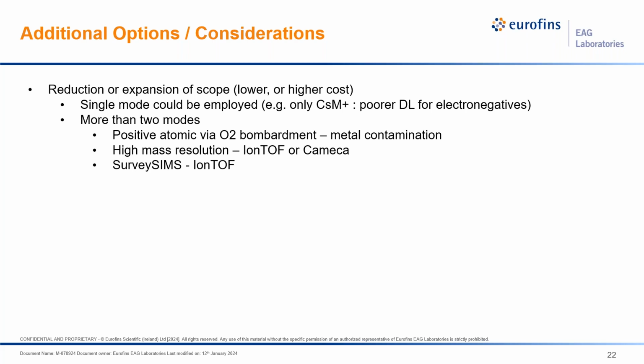So we could also do positive atomic data using oxygen bombardment, looking for other metal contamination. We could also use a different tool, so a high mass resolution is possible on either a time-of-flight tool or a CAMECA tool. This is particularly important if we suspect that some contamination might be a mass interference with something else, and we need to get the true profile. And furthermore, if we need to take a total mass survey without knowing the elements, we can do that with the ToF tool.